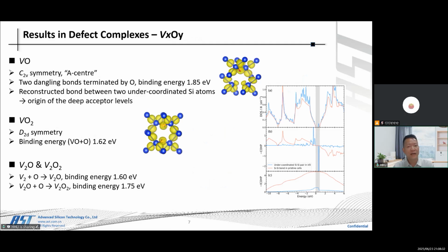Also, complexes such as VO configurations. For example, VO is also called the A center. The two dangling bonds are terminated by oxygens, with a binding energy of 1.85 eV. It has a reconstructed bond between the two under-coordinated silicon atoms, the origin of a deep acceptor level.